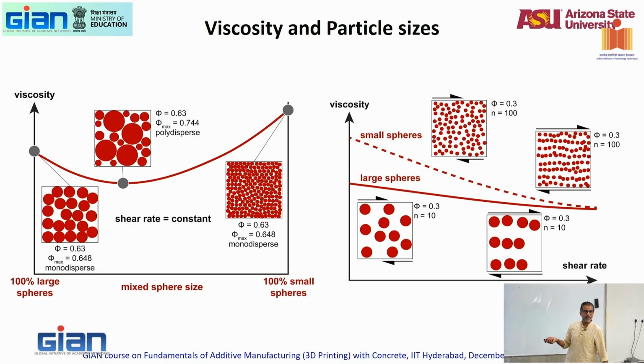Okay. Remember this picture from yesterday? How does this relate now? What was this? Viscosity as a function of volume fraction and sizes. So yesterday I told you we are going to get back here when we talk about packing. So here it is as a function of sizes. With smaller spheres, you get larger viscosity. Larger spheres, you get larger viscosity. Somewhere in the middle, you have a lower viscosity, faster, easier flow. So it's not just one size that does it, it's a combination of sizes that does it.